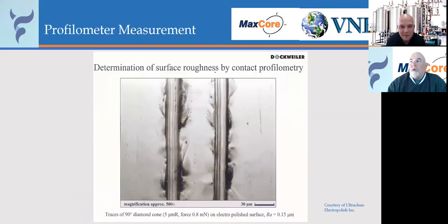Now, when we're also talking about doing surface roughness measurements, a lot of times we'll go in and we'll take a profilometer and we'll put that across the surface of that steel. A profilometer has a diamond tip on the end of it. And when you run that across the surface of that steel, that's what you end up with. That's what you leave back behind. So you're taking your good, smooth, electropolished surface and you run a profilometer across it and you're leaving a damaged layer on the surface of that particular steel that you can't see.